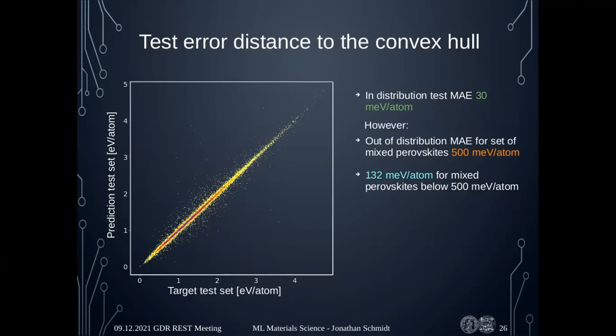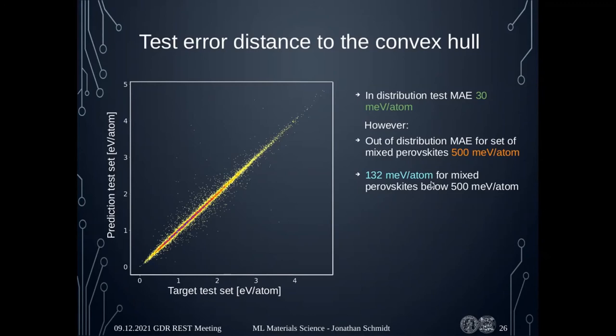However, there is a small problem: this error is for distributions matching the training, validation, and test set. When we removed all mixed perovskites from training, test, and validation, and then tested on them, we get quite a large error. The issue is a distributional shift — these mixed perovskites are on average about 1 eV further removed from the hull than the compounds in our training set. Still, compared to the earlier result where we had 170,000 specific training systems and got 180 meV error, now with zero specific training systems we already get a better error — but not yet sufficient.